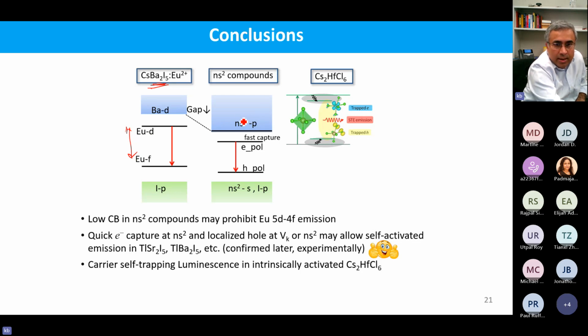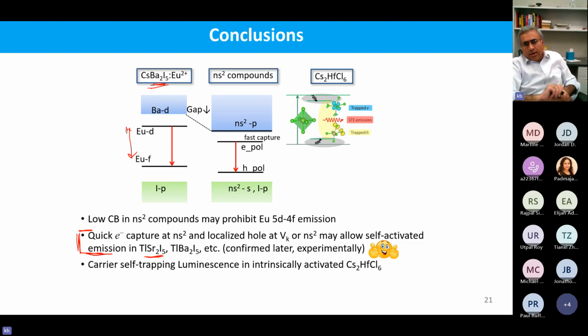For the NS2 compounds, like I said, we do not need europium doping. They most likely can be self-activated and be able to emit. And not only that, after our work, I think they were followed up by experimental investigations, especially this material, thallium strontium iodide, where some of those materials were confirmed to be luminescent without any doping. So that was a good result for us, where we predicted first and the experimental result followed.